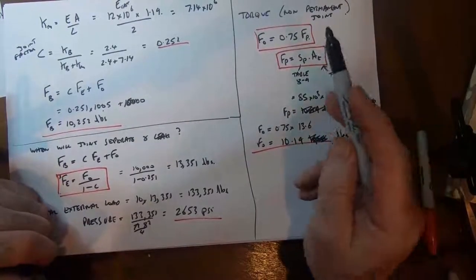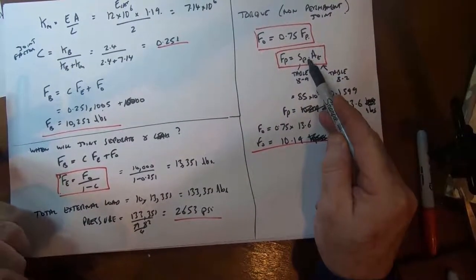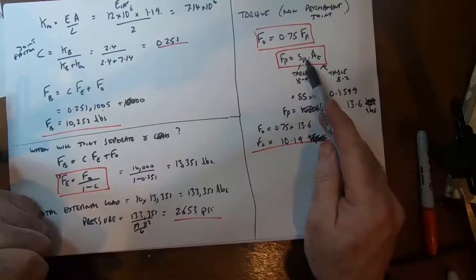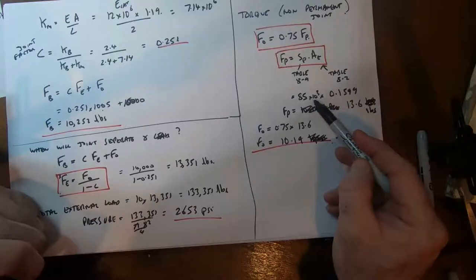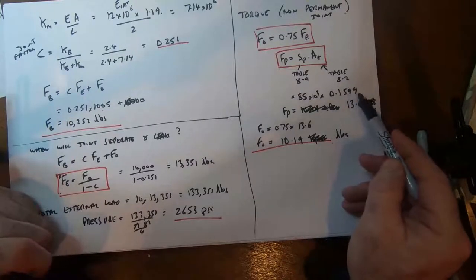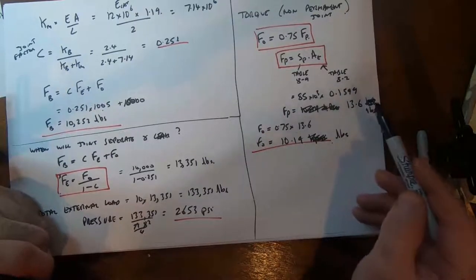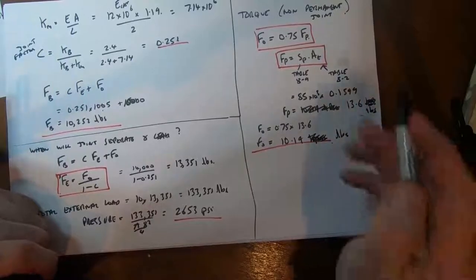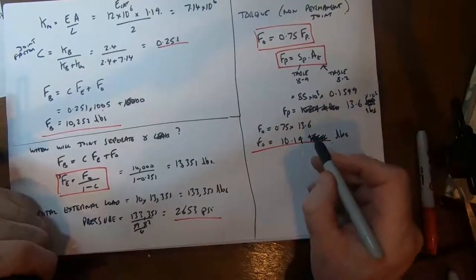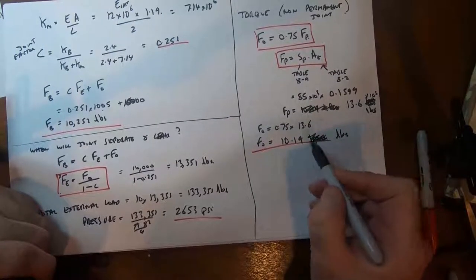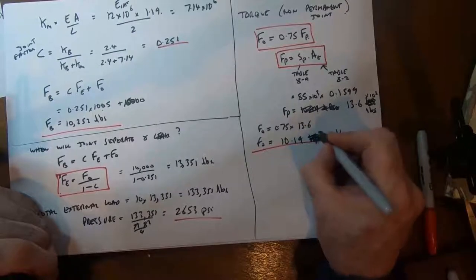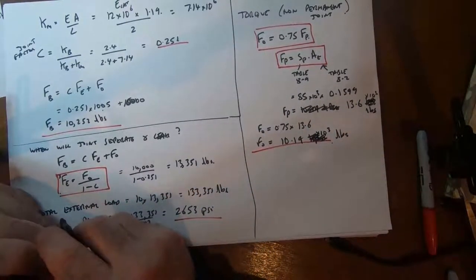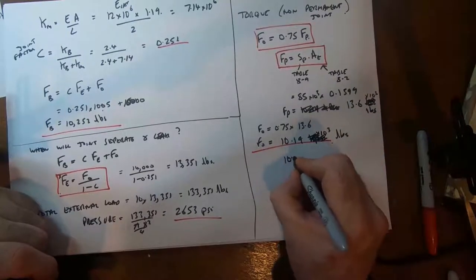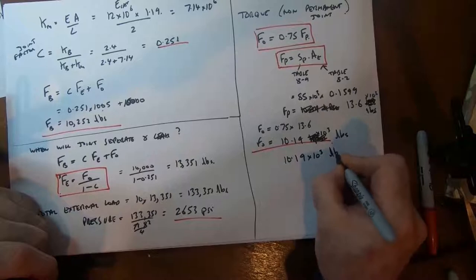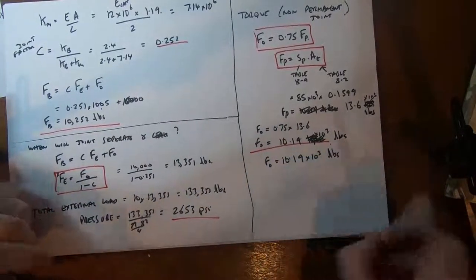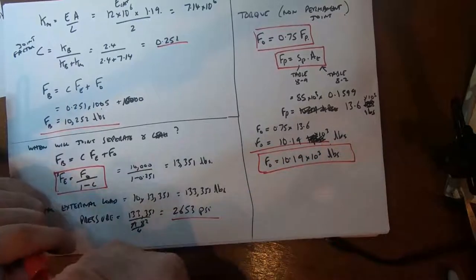Okay, so our proof load is our proof stress times our tensile area. Proof stress in this case from table 8.9 is 85 kpsi. The area is 0.1599 inches squared. Multiply those two together, and that gives me a proof load of 13,600 pounds. And then the preload is 75% of that, so it's 10.19 times 10 to the 3 pounds, which is what they gave us in the problem, 10,000 pounds, as near as possible.